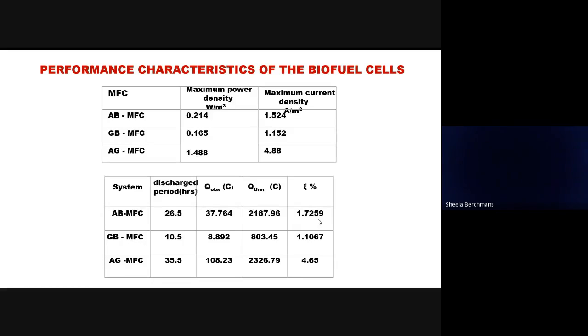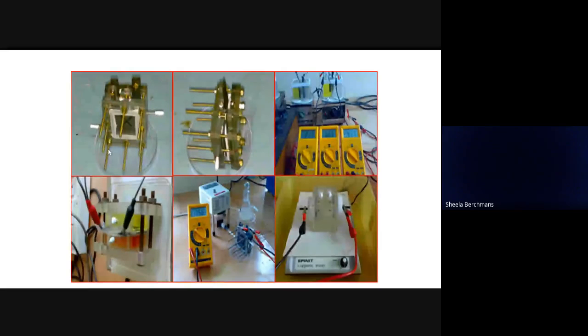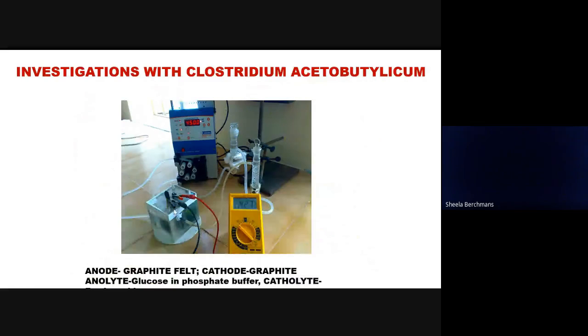We could obtain a maximum Coulombic efficiency of 4.65% and a maximum current density of 4.88 ampere per meter cube, and a maximum power density of the order of 1.5 watt per meter cube. And these are the different designs of microbial fuel cells that were developed in our lab. And this is another